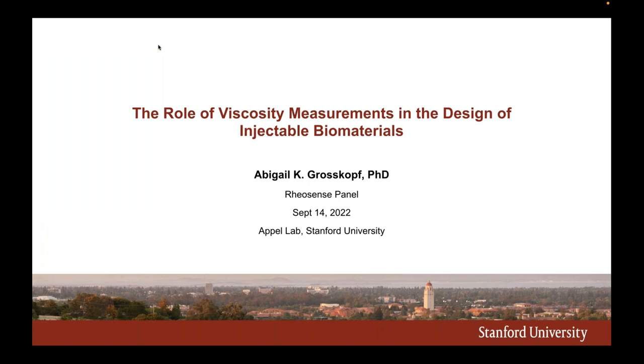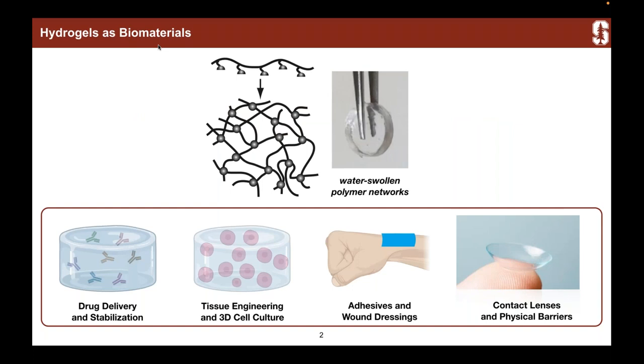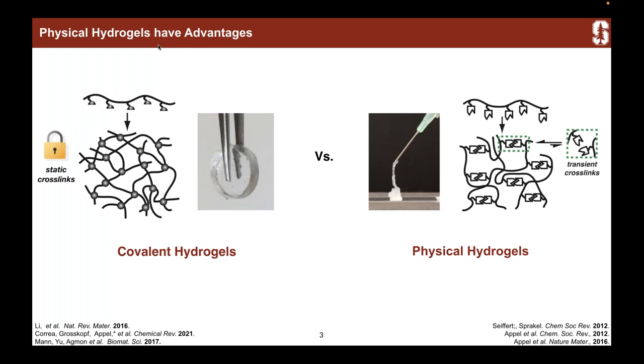So, hydrogels. There are many different key applications. We are particularly interested in physical hydrogels because traditionally one thinks of covalent gels with these static bonds that do not come apart — once they form, they are stuck there as they are. Whereas we're very interested in these physical hydrogels that have dynamic bonds that can come apart and reform. This allows for materials to be, for example, injectable or self-heal after injection. You can tune the dynamics of these bonds for the application you're interested in.